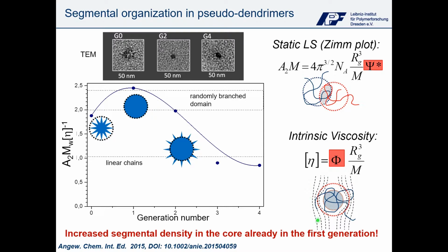Here, the drainage parameter shows us how the solvent molecules are interpenetrating or draining into the outer shell of a polymer coil. Now, taking these two parameters or the ratio of these two parameters into account, we can obviously calculate and describe the segmental density within one macromolecule.